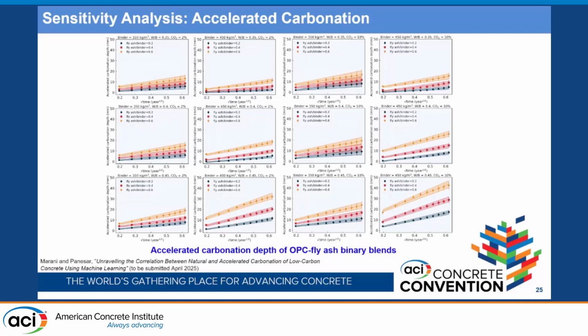We've done lots of sensitivity analysis to find out if the model can capture the synergistic effect of different parameters on the carbonation process. So for example, here we can see that we have different binder content, different water-to-binder ratio, and, in the case of accelerated carbonation, different carbon dioxide concentration. And we can see that for both OPC-fly ash and OPC-GGBFS binary blends, the model was able to capture the effect of, for example, replacement of cement with fly ash on the carbonation.